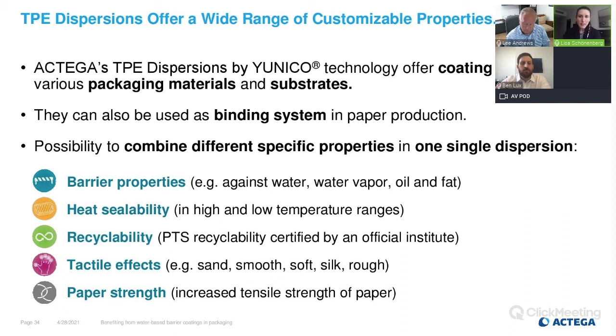Depending on the paper and the application, the amount of these additives can be as high as 20%. Sometimes even higher. And using TPE dispersions, similar properties can be realized with a significantly lower quantity. It also increases the compatibility to the functional TPE dispersion coating, which then leads to better barrier properties.